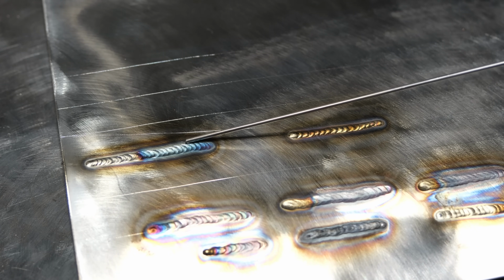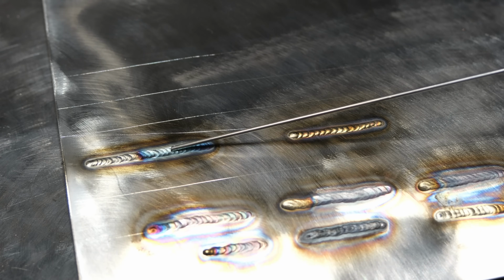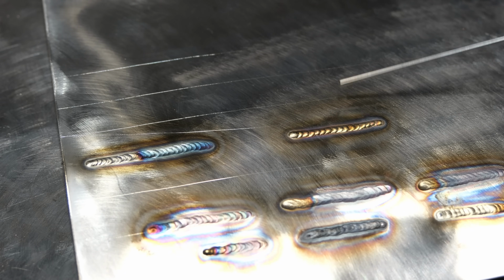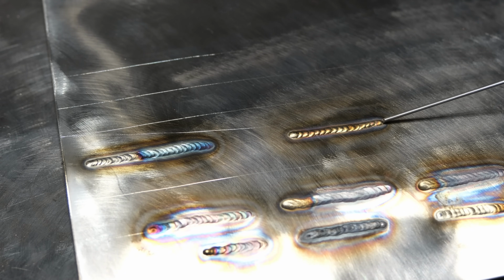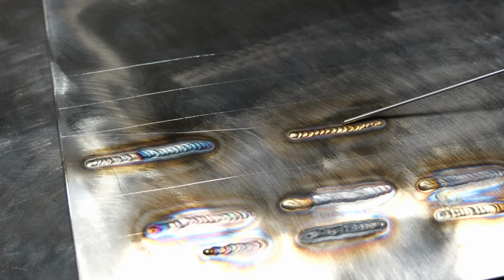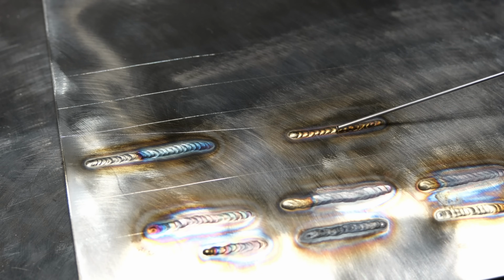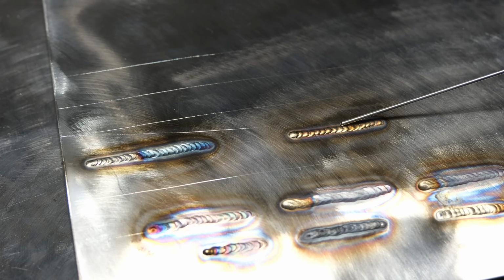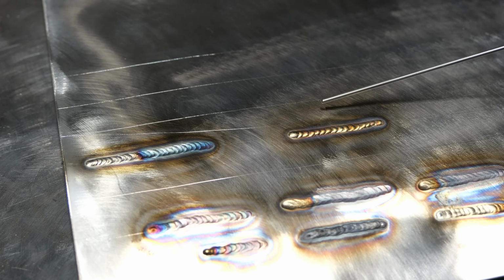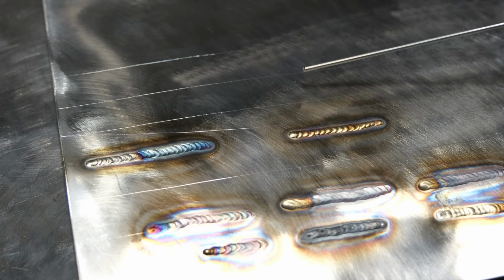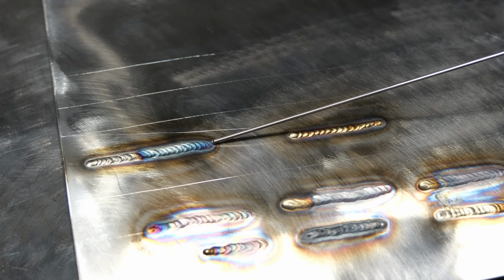I decided to drop the amperage. This was at approximately 30 amps. I dropped the machine down to 25 amps and did this weld. And this to me looks a little bit cold. It's super narrow, it's super high. However, there is some penetration out the back. So overall, this would be acceptable. And it's kind of mind-blowing on this thin a material how 5 amps can make this much of a difference.